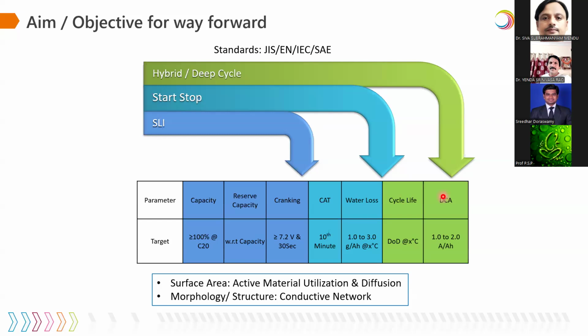As for idle start-stop vehicles, now with this feature, they require higher CAT. CAT means charge acceptance. That means in lesser time, the battery needs to be charged. And also water loss. As I said earlier, electrolysis happens in the lead acid battery, where the water in the sulfuric acid electrolyte is decomposed into hydrogen and oxygen. So the hydrogen will not be there for a long time. It will just go out. So we need to contain these evolutions, because more evolution means more drying out of the batteries. So this needs to be restricted. That's why they have given 1 to 3 grams per Ah. This is for the idle start-stop requirement.